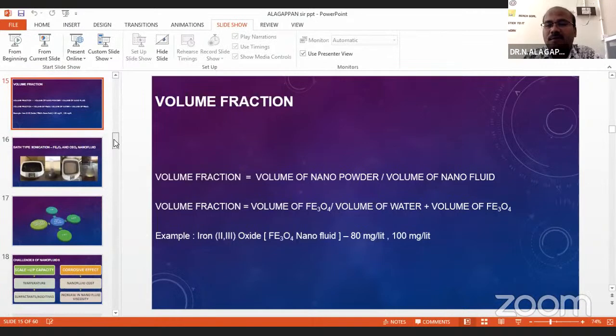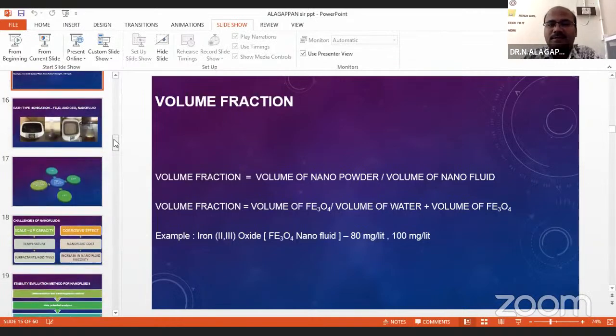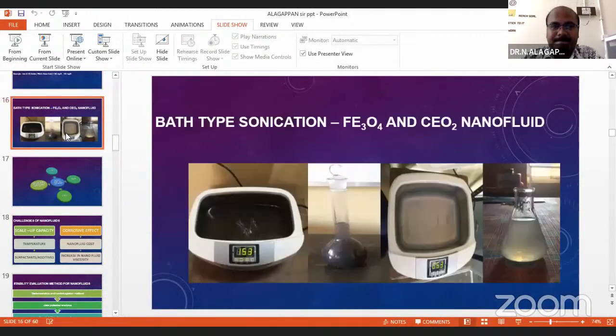So how much volume do we have to take for the fluid for the volume fraction? This is reduction data from the literature. Volume fraction is nothing but volume of nanopowder by volume of nanofluid. So this is what volume fraction is. Here I am taking 80 milligram per liter of Fe3O4 for the reference and 100 milligram per liter for another reference. Next slide, sir. So this is the bath type sonication.